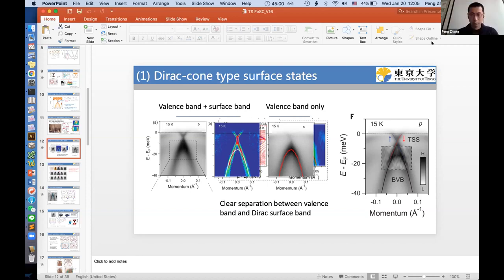Well, it will not be pure DXZ, DYZ after the spin orbit coupling. Yes, sure. But the weight of DXZ, DYZ shows significant oscillations with KZ or with photon energy. So the photon energies that you would associate with gamma and the photon energies that you would associate with Z have a significant difference in the weight of the DYZ orbital, which is what you would expect if it was mostly DYZ mixed with some spin orbit coupling, and then it becomes something that is mostly not DYZ because of band inversion.